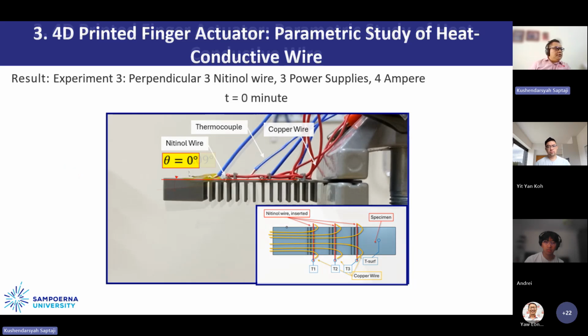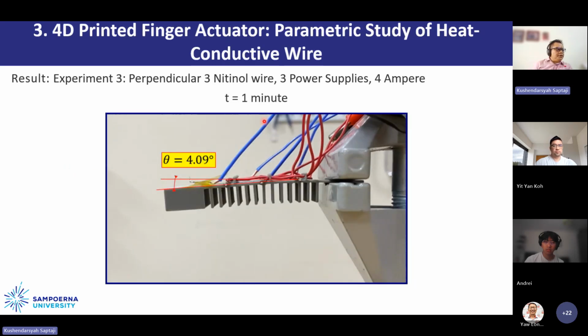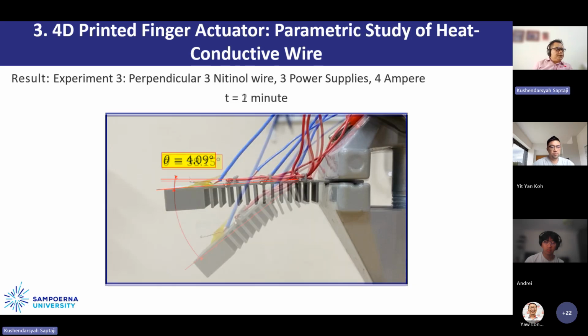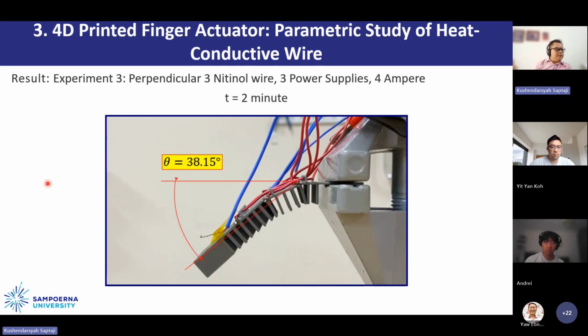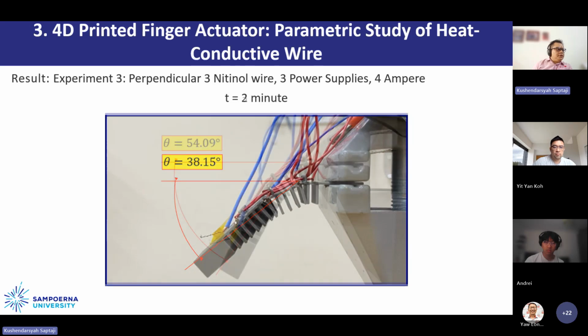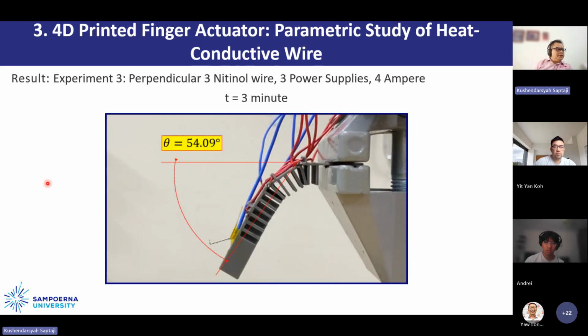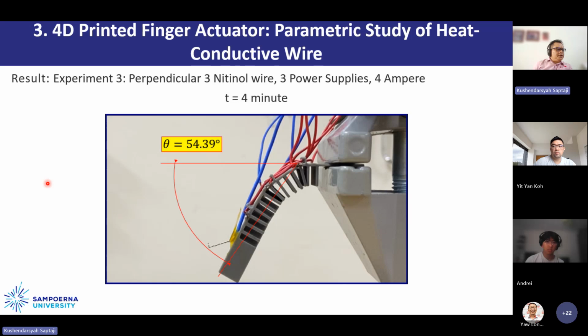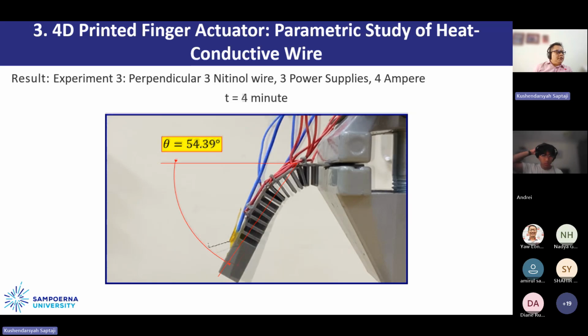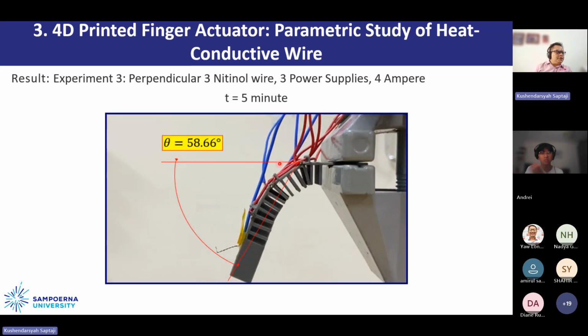after 1 minute, we apply the current. It starts to bend. After 2 minutes, it bends even more. After 3 minutes, 4 minutes, and we stop at 5 minutes. Then after that, we measure the deflection angle in here and also the radius. So this is how we perform the test.